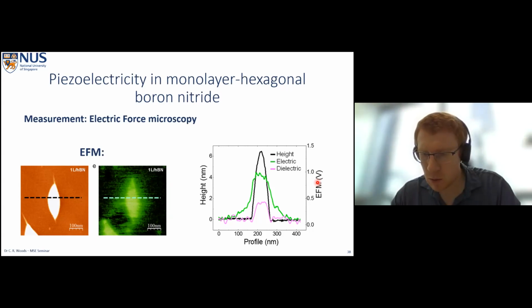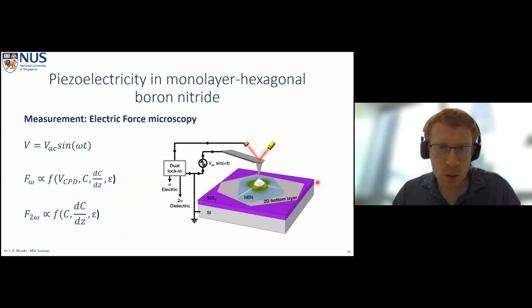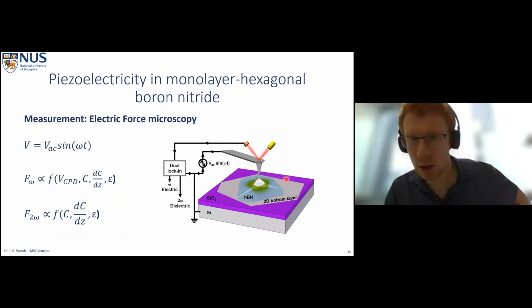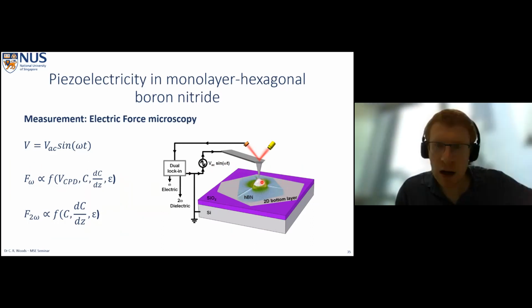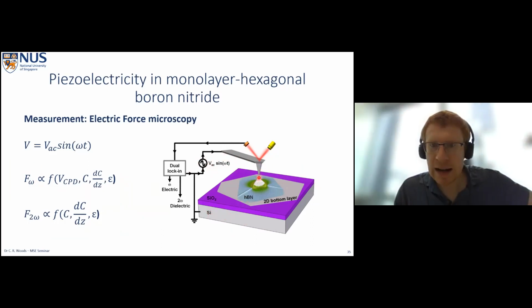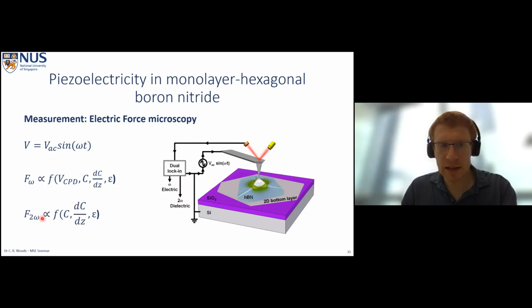So in our case, what we do here is we compare the first and second harmonic. I simplified and went quite quickly over the EFM measurements. But what we're doing is passing an AC voltage between our tip and our silicon. And we measure how much effect the force has on the tip's vibration in the first harmonic and the second harmonic. The second harmonic has a force proportional to a function of a lot of different effects, essentially capacitance and things like this. The first harmonic, however, has all of the same features, but it also has the contact potential difference.